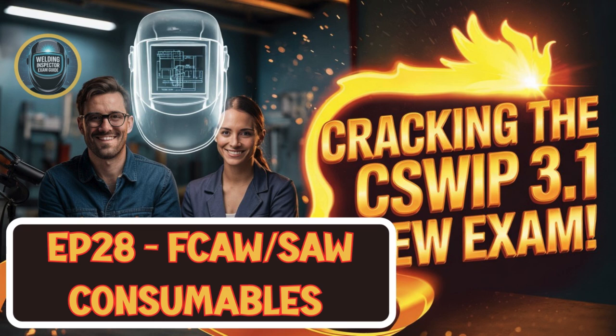Also, the welding positions it's suitable for, flat, horizontal, vertical, overhead, and even the expected level of diffusible hydrogen, which is absolutely crucial for preventing hydrogen-induced cracking when welding certain high-strength or thicker steels. It really ensures you're always picking the right tool for the specific job requirements.